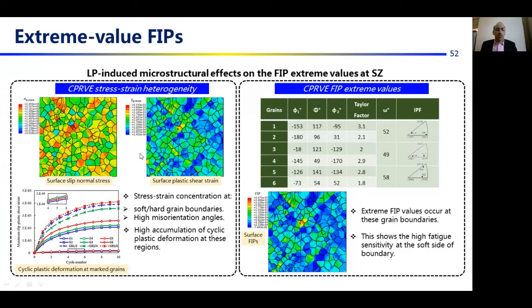And from the extreme value FIP results, you can see from the CPRVE, the stress strain concentration occurs in the boundary of hard and soft grains with the high amounts of misorientation, and the high accumulation of cyclic plastic strain is observed at these regions. And this leads to the extreme FIP value occurring at these soft hard grain boundaries, and shows the high fatigue sensitivity at the soft side of these boundaries.